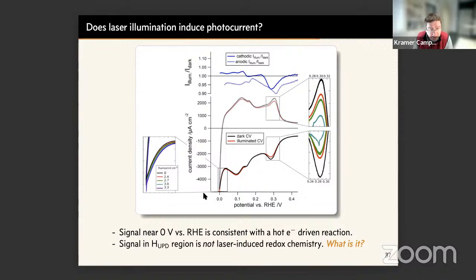So if you zoom in now near hydrogen evolution, what you see is that if you look at, say, a constant current density and you increase fluence of the laser pulse, you go from 0 up to 3.3 millijoules per centimeter squared, that the onset potential of hydrogen evolution goes more and more positive. Similarly, if you stayed at a particular bias, say, 0.02, and looked at currents, the hydrogen evolution current would be larger under larger illumination. So this is now the first observable.